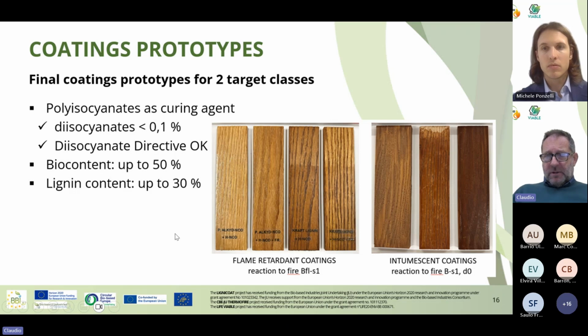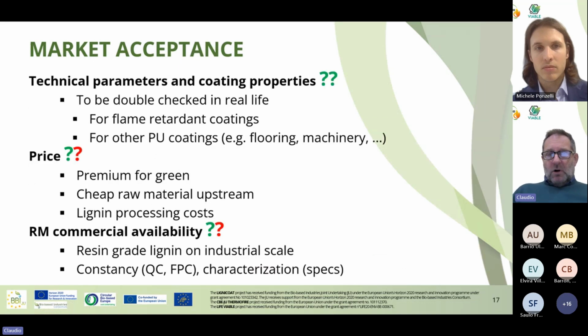You can see pictures of the materials that we have made. Some of them don't look that bad. Some of them are, well, a bit dark or not really as transparent as we wanted. Basically, those that can pass the simpler reaction to fire test allow us to use less additives, a smaller amount of lignin, different conditions, and they look better. Those that need higher fire performance need more additive, and in general, they don't look as nice from an aesthetic point of view. All these points will have an effect on the final market acceptance.